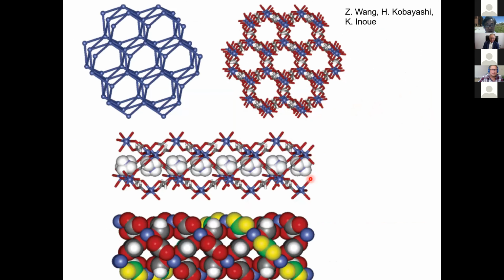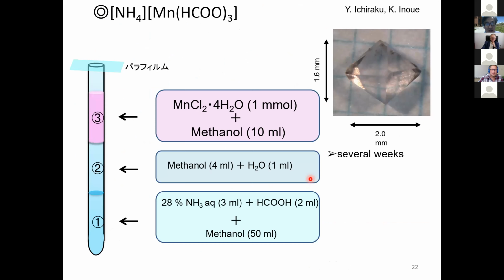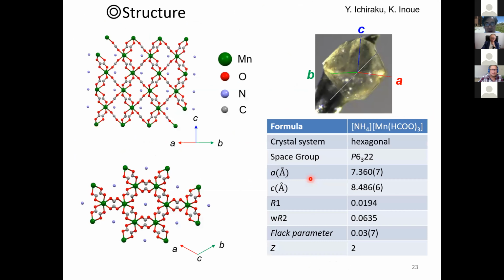And the structure is like this. This is a bit busy, then let's go further. This is an X-ray structure on this sample. The important thing is the space group is P6322. This is chiral, and this space group is the same as the previous one, chromium niobium sulfur.